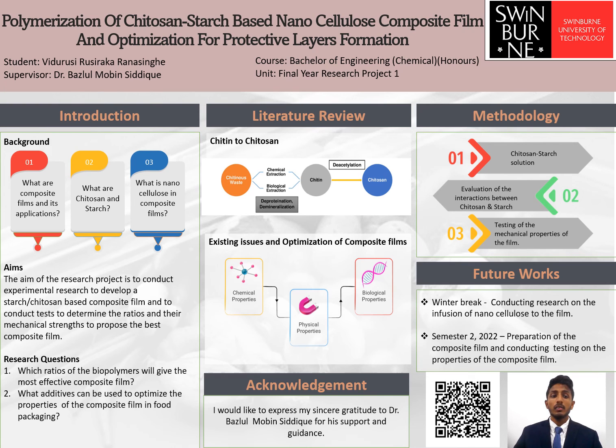In the third part, the mechanical properties of the composite film will be studied using equipment such as the Instron Universal Machine for testing the tensile strength and elongation values of the film. The gravimetric modification of the ASTM method can be used to find the water vapor transmission rate.